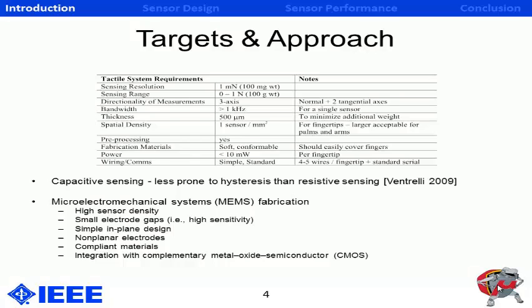So my work is focused on capacitive sensing. The approach we used is capacitive sensing, and we chose this over resistive sensing since resistive sensing has been shown to suffer from hysteresis. The fabrication process is a MEMS-based fabrication process, which in itself has several advantages. With MEMS fabrication, you can have high sensor density, you can fabricate small electrode gaps, which I'll emphasize later in the talk, you can create simple in-plane designs, you can integrate non-planar electrodes, you can use compliant materials, and you can even integrate with CMOS fabrication.